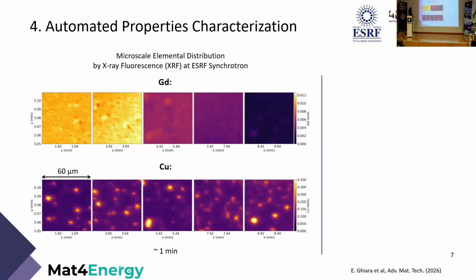At ESRF synchrotron in Grenoble, we were also able to perform X-ray fluorescence maps with a micrometer scale resolution, which allowed us to verify the fact that the rare earth truly mix during the deposition at a micrometer scale. And also we were able to detect the copper oxide secondary phases that we have inside the film. And this is really helpful for us because at the same beamline, we can also perform X-ray absorption spectroscopy. So to be able to detect the copper phase and separate it from the REBCO phase, we can perform XAS spectroscopy on a region that we are sure is pure REBCO film.